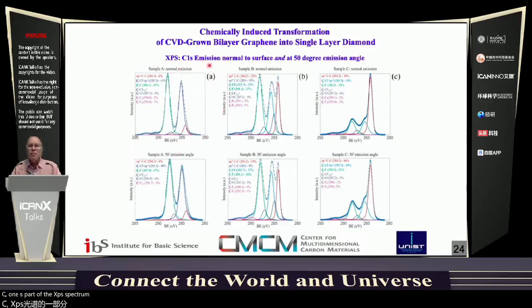I'll go into some detail, but let me tell the bigger story and encourage reading our paper if this interests you in great detail. But here we're looking at the C1S part of the XPS spectrum. And Pavel looked at emission normal to the surface and then also at a 50 degree angle. Now at the 50 degree angle, you're addressing the sample, the thin film, in a different way. You're collecting from a thinner layer closer to the surface.